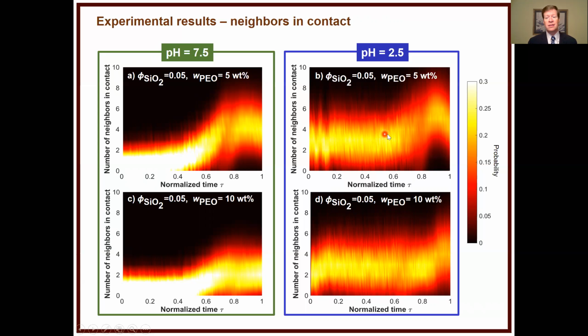Now, as things dry, what happens is, we said the concentration goes up, and mainly this is a compression of this film, and it's breaking the gel. So you can think of this as a very chemically driven process, and everything at 2.5 is a very mechanically driven process. Now, for many people who look at rheology and coatings, maybe that's not too surprising. But again, thinking back to being able to measure this specifically, the structure is kind of new in this field.